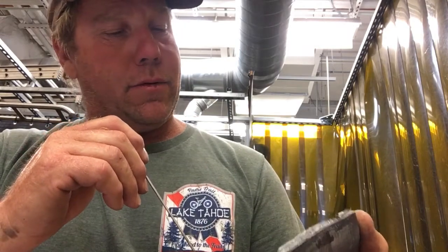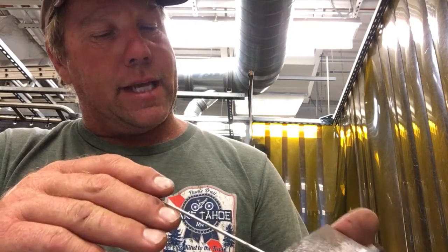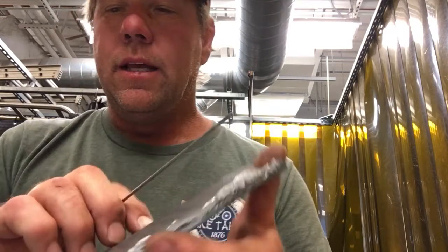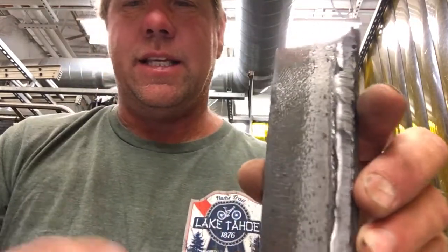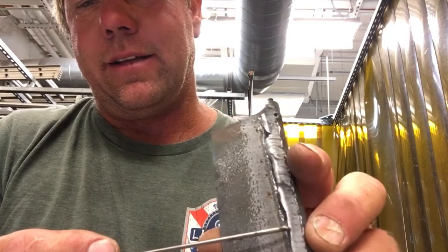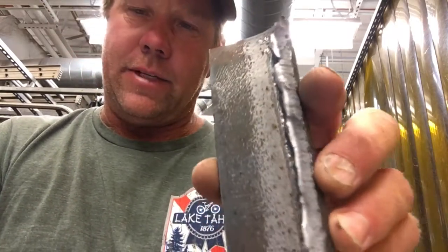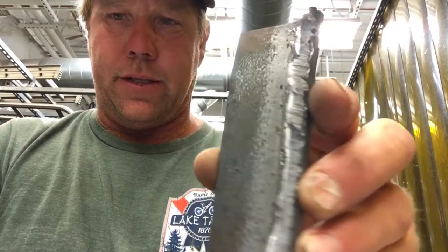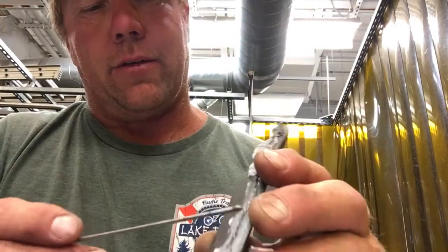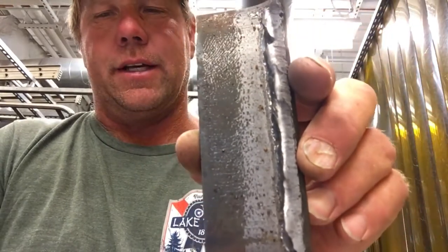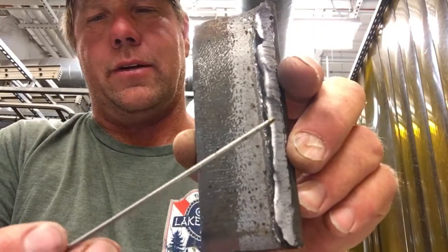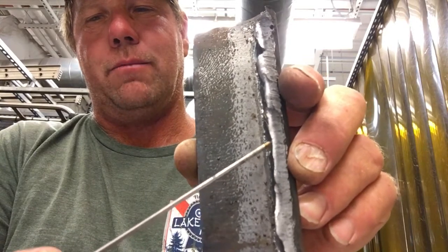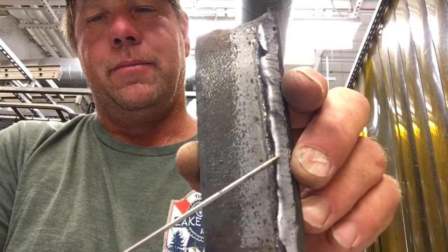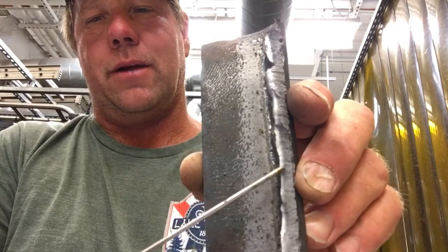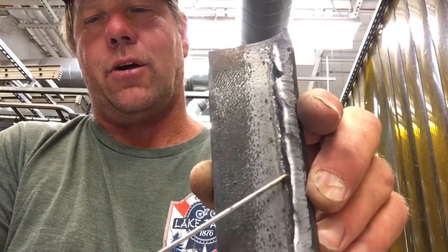Hoping to see something a little bit more, but I don't. Doesn't mean my weld's perfect, it just means I don't see any great examples of things I want to show you. Kind of interesting here. You see this little edge right here? How it's all shiny, but it doesn't go very deep. Every time you weld, the grains get a little bigger and a little bigger and a little bigger. This is all grain growth in here. You can kind of see the size as they go. And so what happens from this dull area here to this shiny area here, this is from me water cooling that last weld. Didn't want to wait anymore. These I let run hot. This one I water cooled, and you can see that kind of surface hardening of that material.